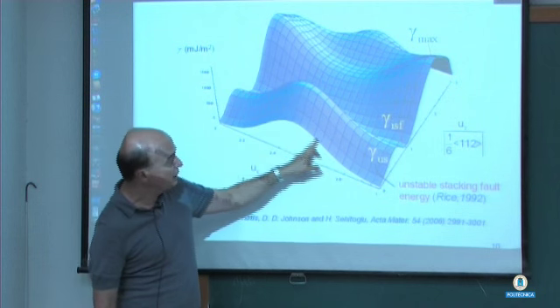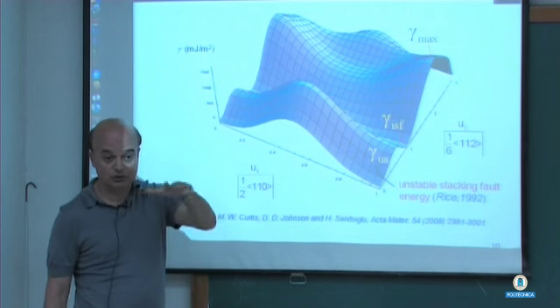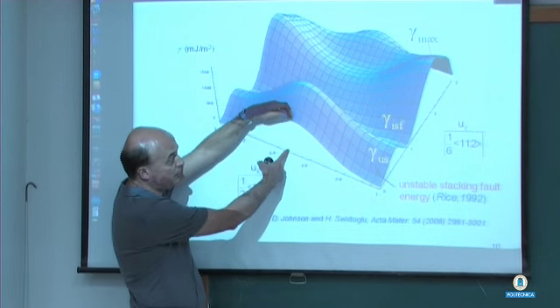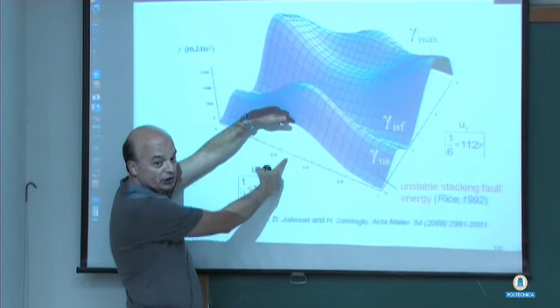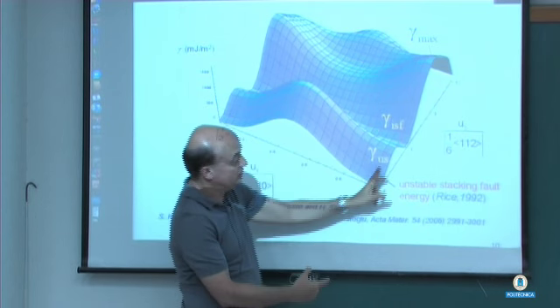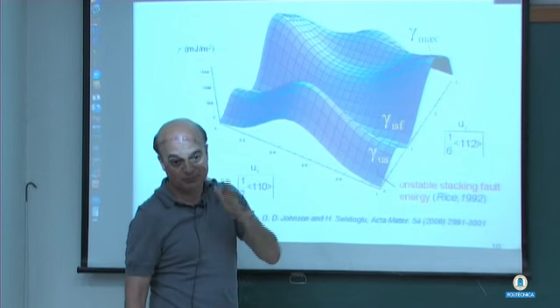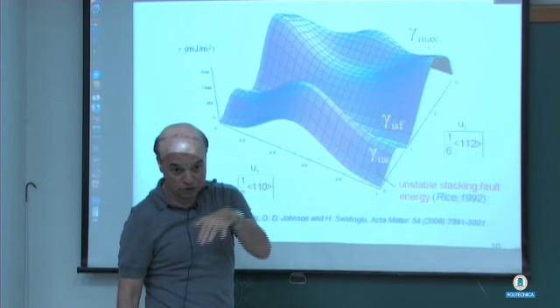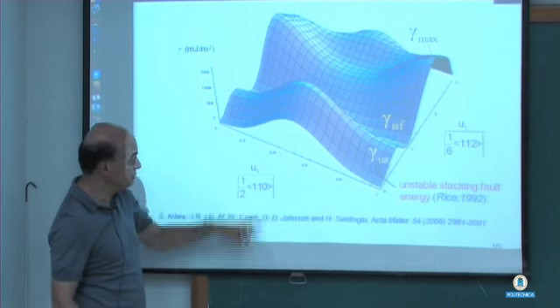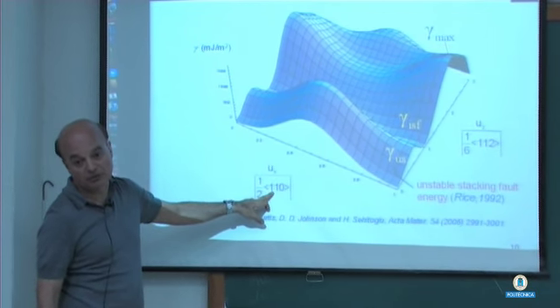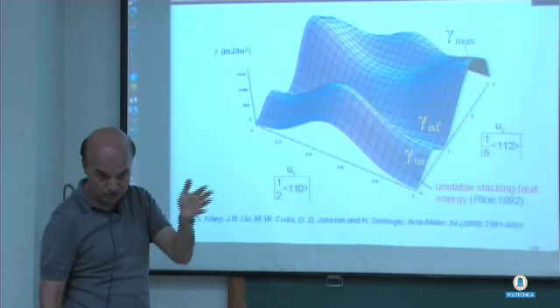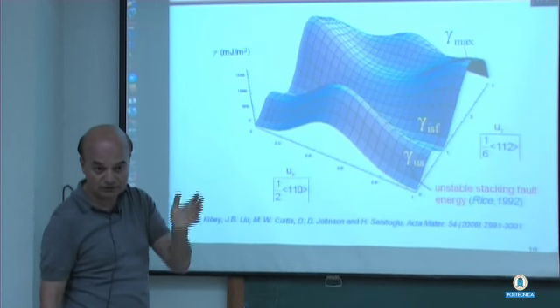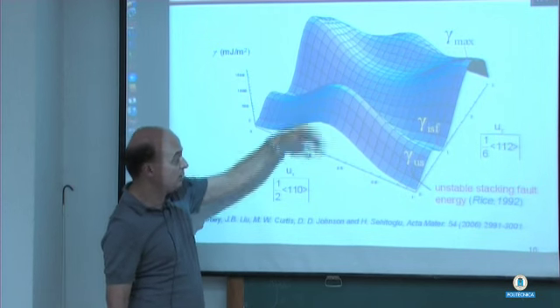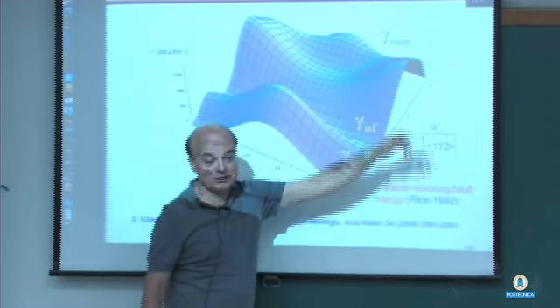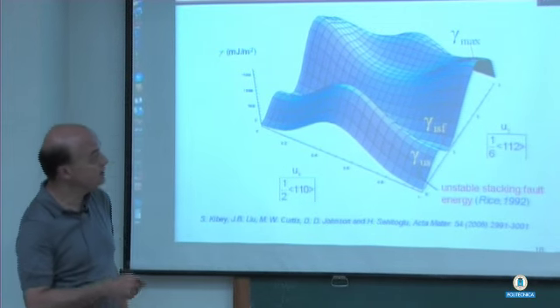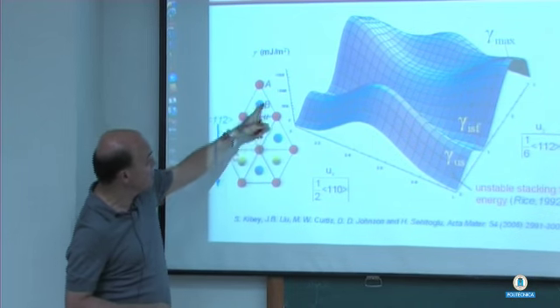But this would be the energy barrier if you moved a full dislocation, a perfect dislocation. You could see the energy barrier associated with that is quite large. That's why in FCC metals the partials form, and you get the motion of the partials rather than the full dislocations. That would be the motion along the 110 direction, which is what we teach our students in elementary dislocations or elementary material science. This is again all the 111 plane. That's the 110 direction. This will be the 112 direction. So that's the gamma curve, and that's the motion I just described.